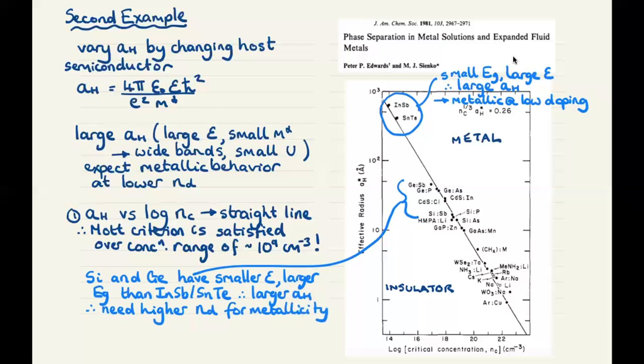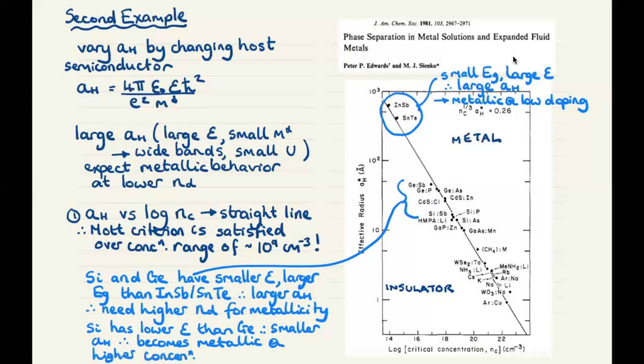And in terms of their ordering, silicon has a lower dielectric constant than germanium and a smaller hydrogenic radius, and so becomes metallic at higher concentration. I see a typo here. It shouldn't be larger hydrogenic radius, but smaller, I'm sorry. They have a smaller dielectric constant, then they also have a smaller hydrogenic radius.